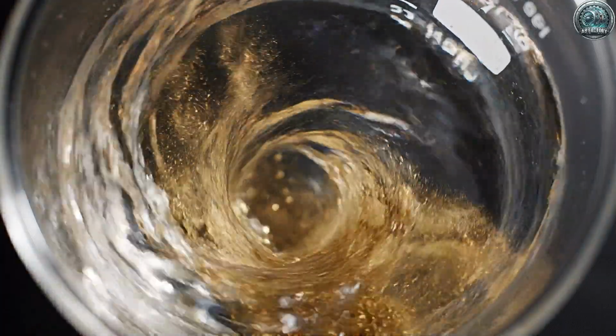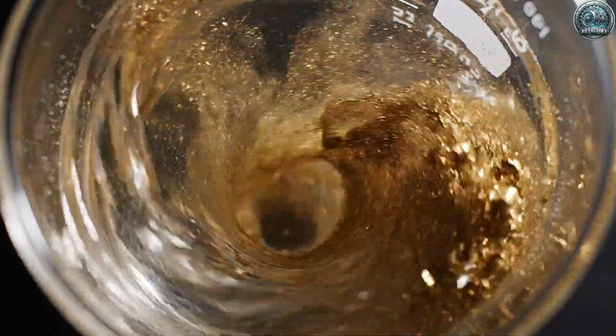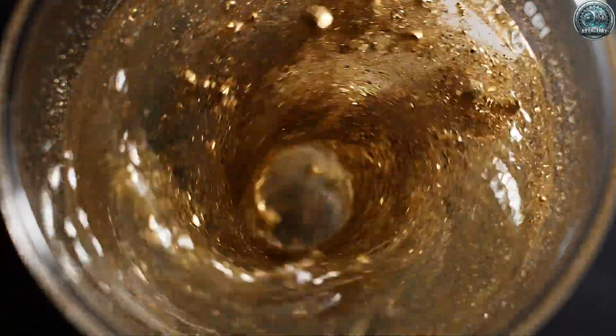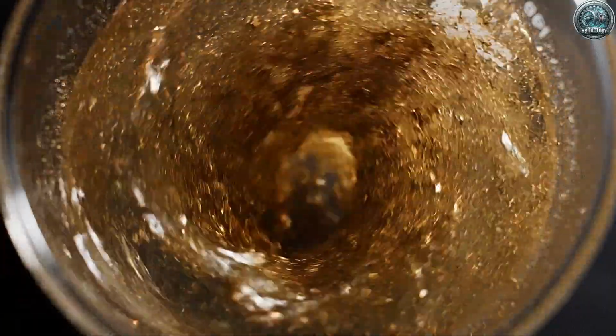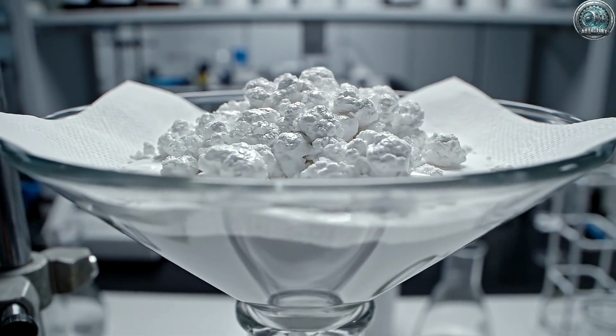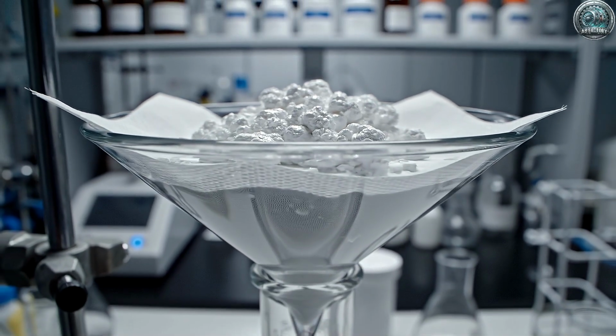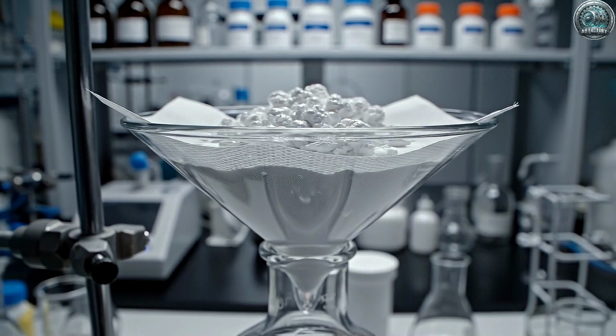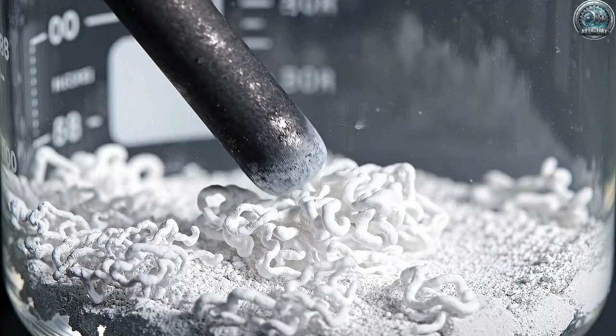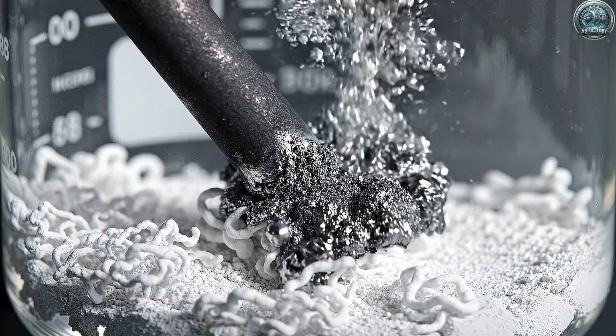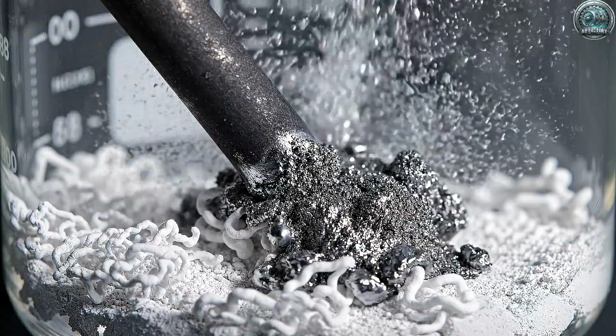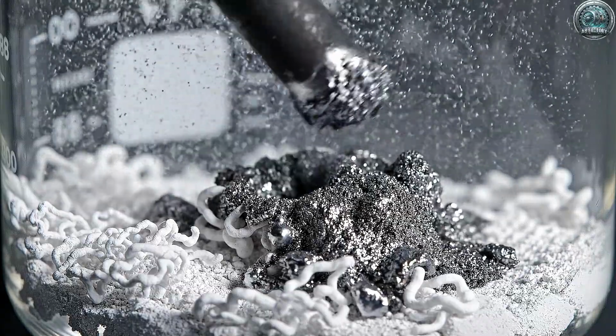Repeated washing with distilled water removes any remaining acid, ensuring the gold dust reaches 99% purity. Meanwhile, the white solids filtered out earlier are identified as silver chloride, ready for their own transformation. A metal rod triggers a rapid exchange reaction, converting the white chloride compound into metallic gray silver.